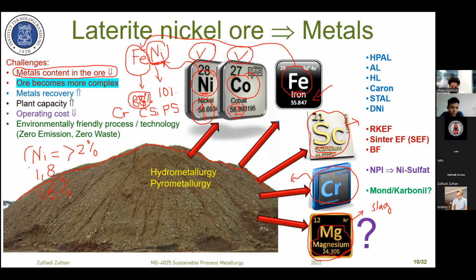For sure, if we have low nickel content, at the end we should put in more energy. The energy requirement will be high in order to process this low grade of nickel. That's what we have now. Ore becomes more complex. It's also a big challenge. I will inform you later that for nickel smelting, we should consider the ratio of silica to magnesia. We should consider this.